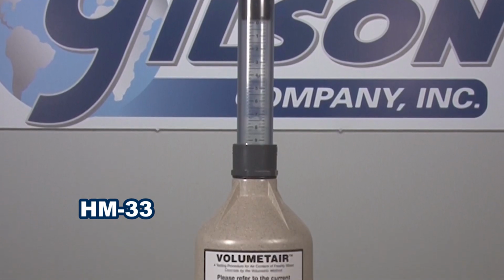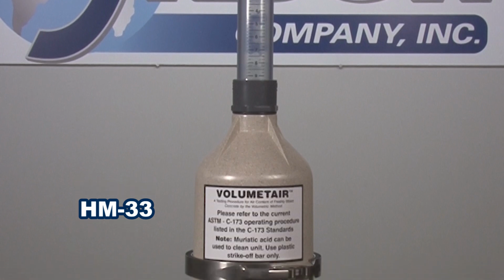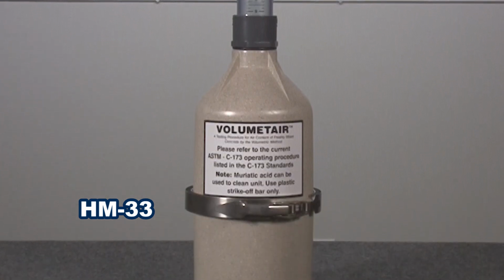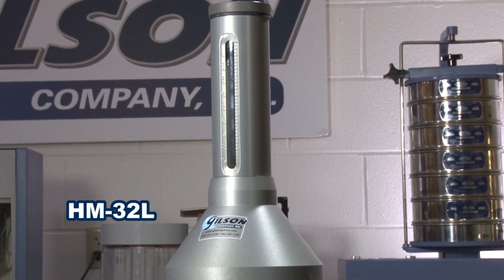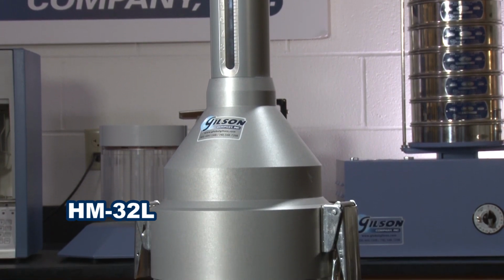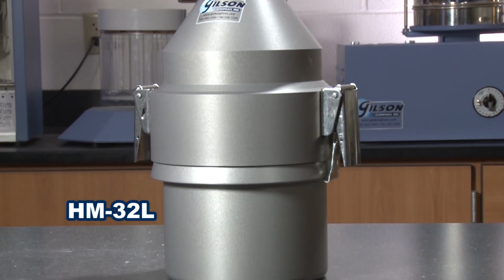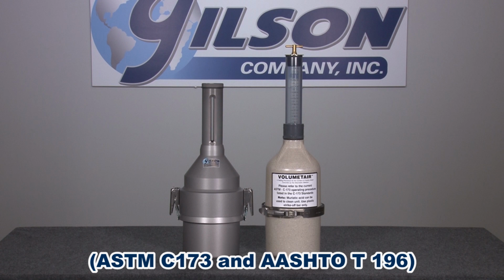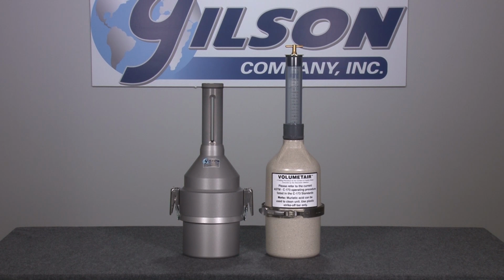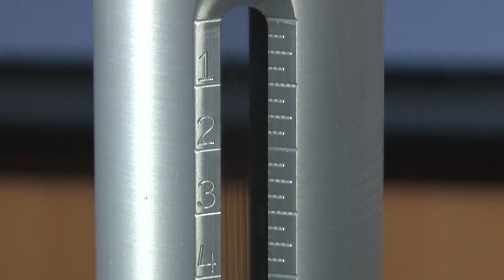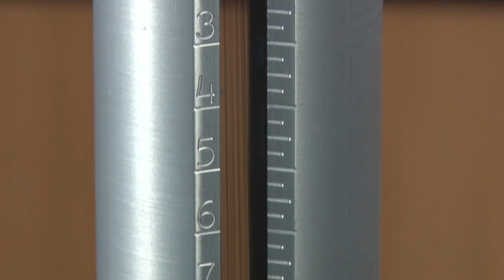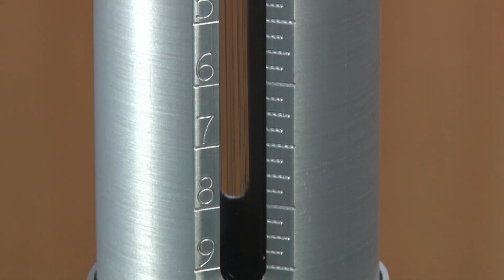Volumetric air content tests start with a concrete specimen of a known volume, consolidated within the sealed volumetric unit. After consolidation of the concrete in the base, a combination of water and alcohol is added. The vessel is then agitated vigorously. This action essentially washes out air voids, leaving only solids and liquids within the vessel. The percent of air is easily obtained on the sight tube scale.